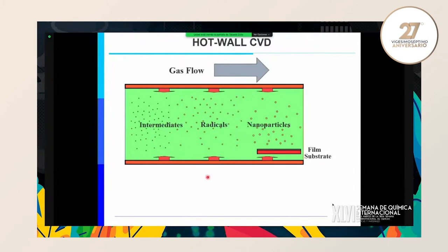So in common CVD, we use this kind of tube furnace, which is called hot wall CVD. The walls are heated and the substrate is indirectly heated by radiation from the wall and heat conduction of gases. So in the hot wall CVD, homogeneous reactions become significant, forming a large amount of intermediate radicals and nanoparticles.